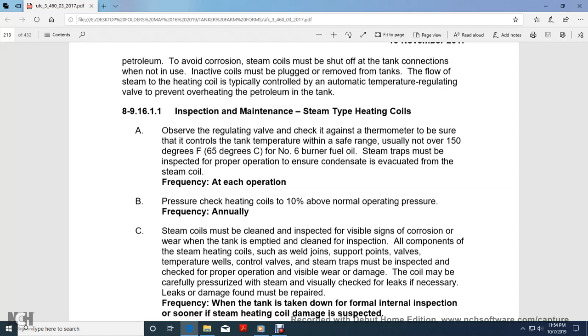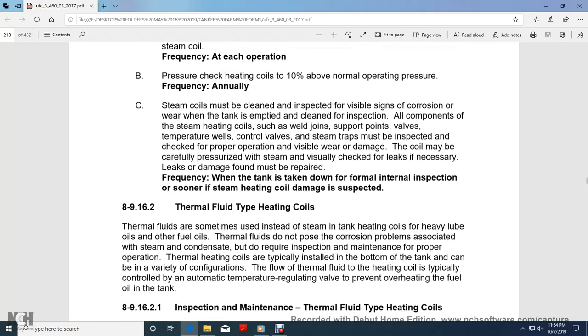Pressure check: check heating coils at 10% above the normal operating pressure annually. Steam coils must be cleaned and inspected for visible signs of corrosion whenever the tank is empty. Cleaning with inspection of all components of the steam heating coil, such as joints, support points, valves, the temperature well, the control valve, and steam traps, must be inspected with a check for proper operation. Wherever damage of the coil is visible, it may be carefully pressurized with steam and visually checked for leaks.